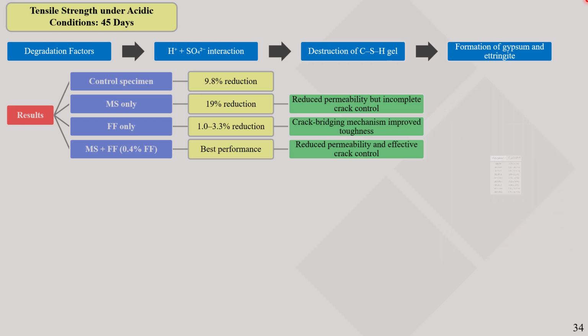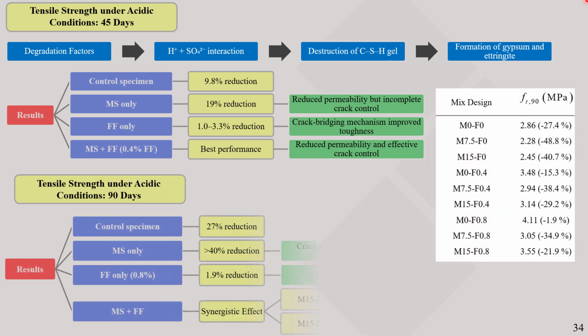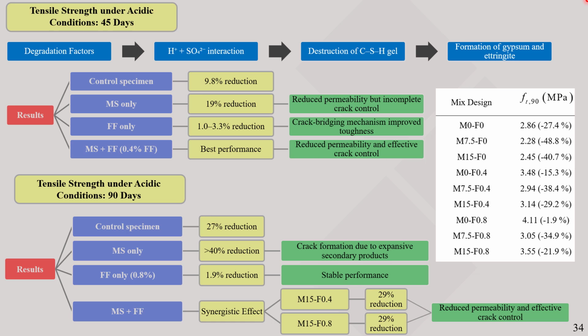0.4% fibers were used. In the 90-day acidic condition, samples containing only Forta-Ferro fibers showed only a 1.9% reduction in strength compared to the non-acidic condition, indicating stable performance. Combined samples with the highest fiber and microsilica content also exhibited effective synergy, with a strength reduction of approximately 22%, performing better than the reference sample.